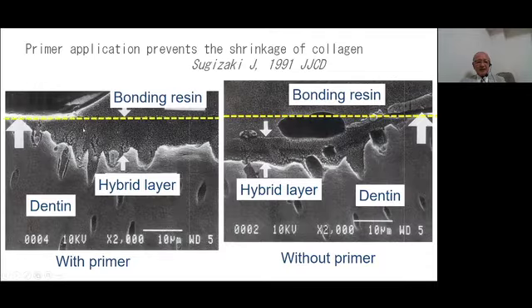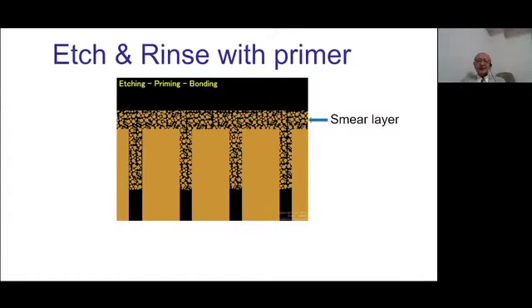On the other hand, in the case of primer application, the hybrid layer formation can be seen here, and the top surface of the hybrid layer is equal to the original dentin surface. It means that the collagen layer did not shrink. They kept the original height of the structure. So that's why the primer is very effective to re-expand the shrunk collagen layers to accept more bonding resin into the demineralized dentin. That's why the durability was very good.